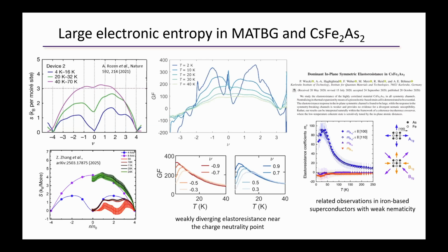So I think that this is the most careful way that this has been done, to my knowledge, where you basically try to decompose the different anisotropic and isotropic elastoresistance coefficients, and then compare whether the effect that you're seeing in the gauge factor is predominantly from the isotropic channel or predominantly from the anisotropic channel. And the story in iron-based superconductors is that the stoichiometry determines what the answer is.